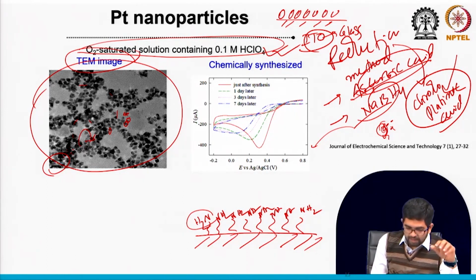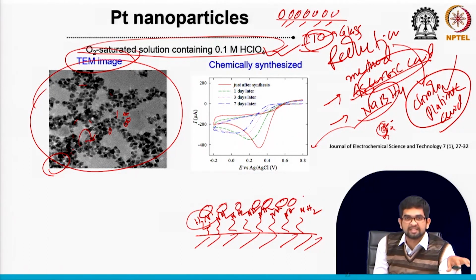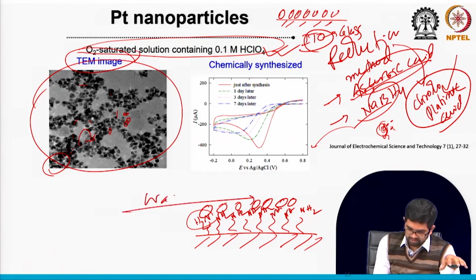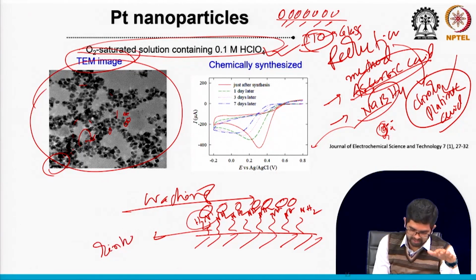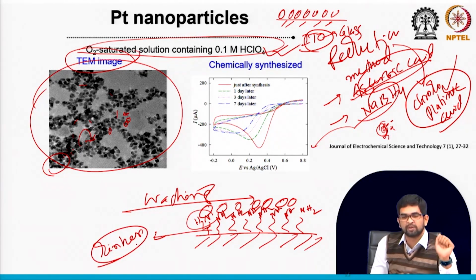Now, this amine and nanoparticle, this gold or platinum, they have some interactions. So, they will be very easily attached on the surface and they will not easily detach when you wash, because you need some washing, no? So, when you are washing the surface just after synthesis, they will not easily detach. That is why it is recommended when you drop some nanoparticle, let us use some linker, this kind of linker you can use. They will help bind the nanoparticle on the surface.